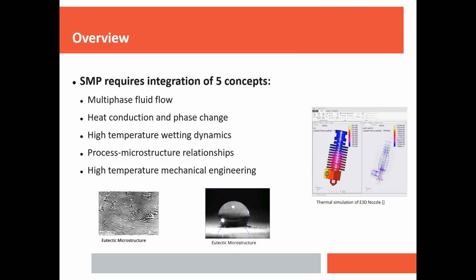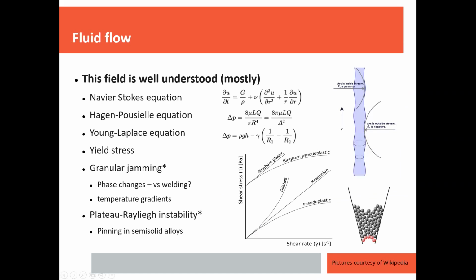Semi-solid metal printing is difficult because it rests at the corner of 5 different fields, more or less. You have to consider multi-phase fluid flows. You have to consider heat conduction and the phase change of the metal, wetting dynamics at high temperatures, which are very different from wetting dynamics at room temperature, and process microstructure relationships, and then general high temperature mechanical engineering. So the fluid flow is mostly well understood. It's a very developed field.